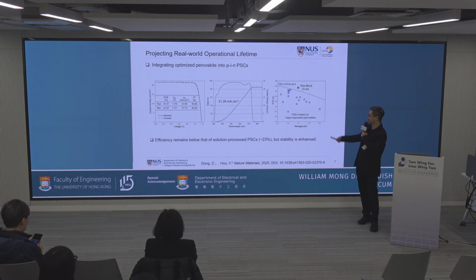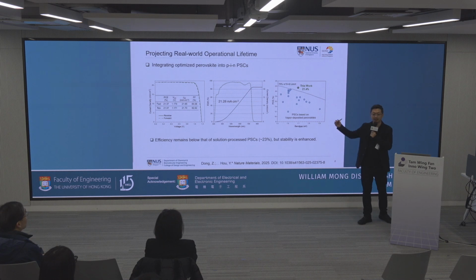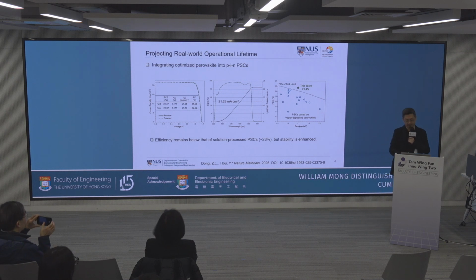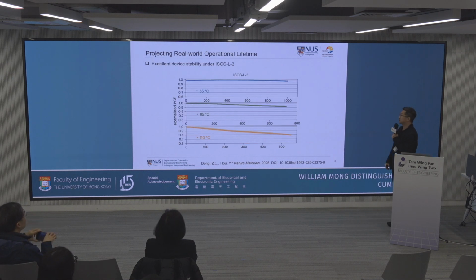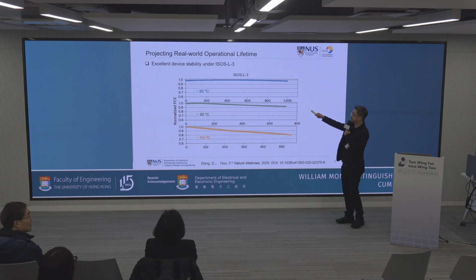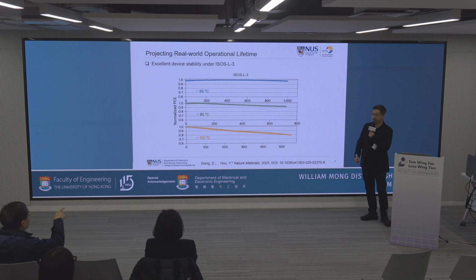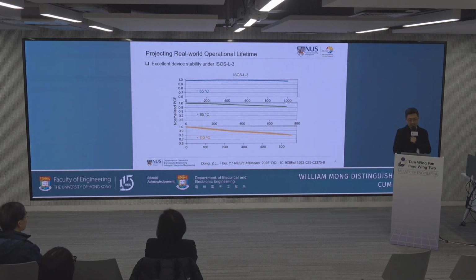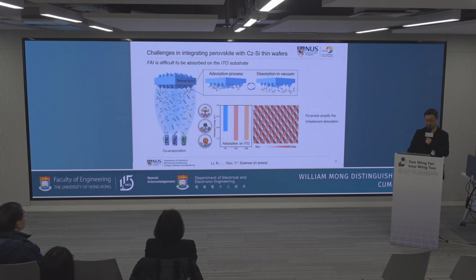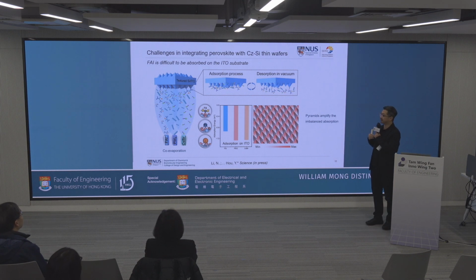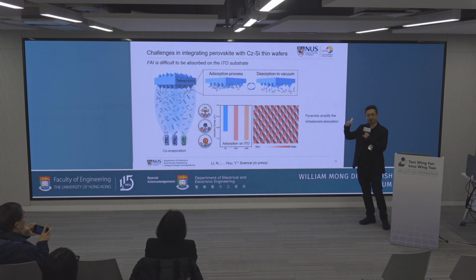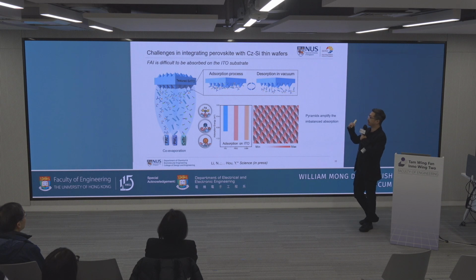But we just see the advantage of this one actually is okay efficiency, but the stability we see is much improved. And so this is the stability result if we age them at 65 degrees C, 85 degrees C, even 110 degrees C, and then we can do this accelerated aging test. And yeah, so it gives us the confidence to make a conformal growth perovskite onto the silicon. And that's the kind of the baseline. We know how to evaporate stable, okay efficiency, wide band gap perovskite, and the next step is we need